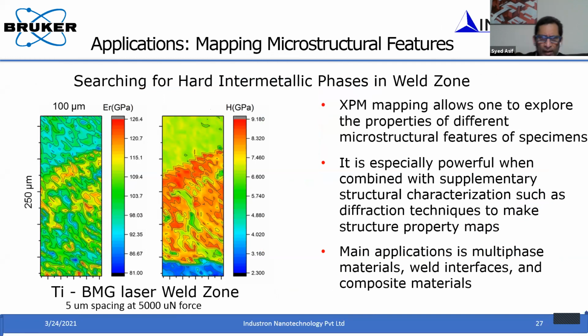Again, this is another example. This is a titanium and bulk metallic glass weld zone, where you can see the top part is the titanium, the bottom part is the bulk metallic glass. When you do the weld zone, you do develop intermetallic phases at the weld zone, and they have a much higher hardness compared to both materials. And you can nicely see, when you do this mapping technique or a profile across, basically from one material to another material, how the interface is changing, how the modulus and hardness are changing at the interface.